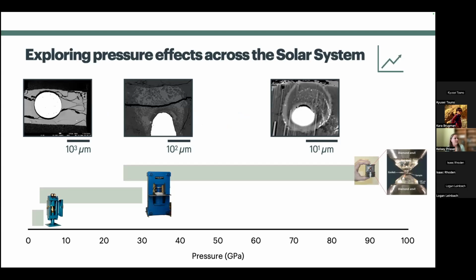But one of the hard things about this is as you go to higher pressures, your sample is getting smaller. Everyone in this audience is probably familiar with that, as it's a function of the techniques that we're using for obtaining high pressure in these experiments. I have here backscatter electron images of a piston cylinder experiment to the left, a multi-anvil experiment in the middle, and a diamond anvil cell experiment to the right. These are backscattered electron images, so again, the bright white is our metal and the light gray is our silicate melt.